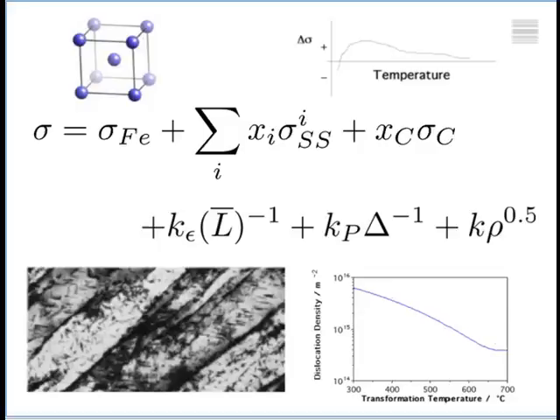What you cannot see clearly here, but it's evident in the contrast that we have in this transmission electron micrograph, are line defects called dislocations. And dislocations are contradictory in the sense that their presence makes a steel weaker, but if you put enough dislocations in the material, it becomes stronger. So as we increase the density of dislocations here, we will get a stronger steel. And you can increase that density either by exploiting displacive transformations or by deforming the steel and getting work hardening.